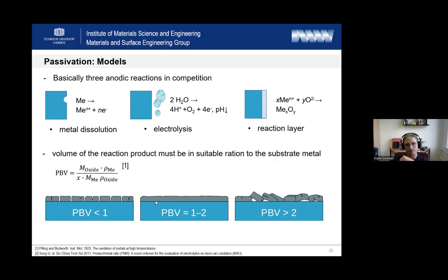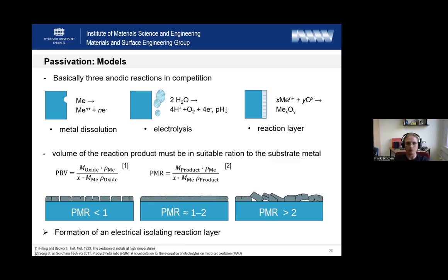And in case that they are in suitable range, between 1 and 2, you get an oxide which completely covers your metallic surface. And if this ratio is too high, for example, in case of iron and iron oxide, you will create your oxidic layer, but this oxidic layer will flake off permanently. And this system will also not be electrical isolating. And this is really important in PEO. And in PEO, we don't